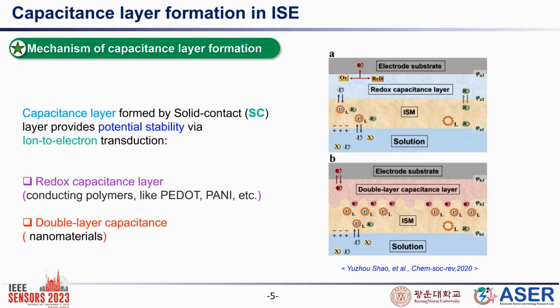The issues I have mentioned are 3 kinds of problems. To eliminate these problems, we need to use nanomaterials that are hydrophobic as well as conductive and of high surface area, because we want to make a capacitive layer, right, a double layer capacitance. Materials with high surface area will favor the formation of a double layer capacitance, and if it has the hydrophobicity property, it will eliminate water layer formation. So, considering all the properties, my goals are low potential drift, a very stable response, and flexibility in my research.